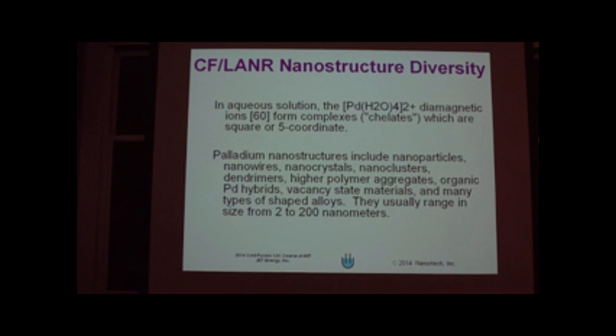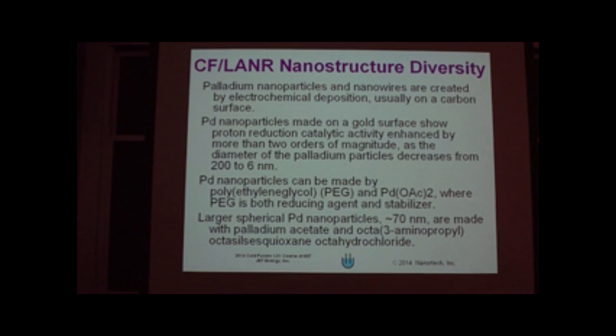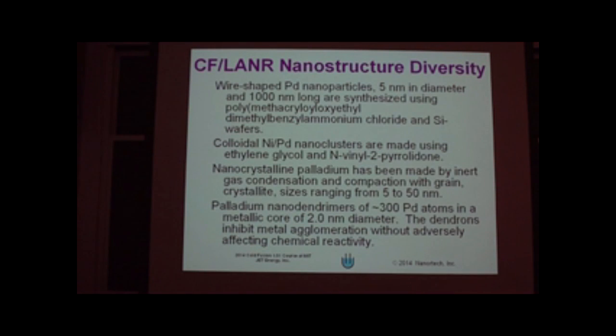Okay, nanomaterials. If we put palladium in solution, we get a chelate. There's all kinds of palladium nanomaterials we've started looking at. Some of them form dendrimers, which are really gorgeous structures up to 200 nanometers. We can make them, you can go through all of this. There's quite a number of palladium materials that are being looked at or we're looking at now.